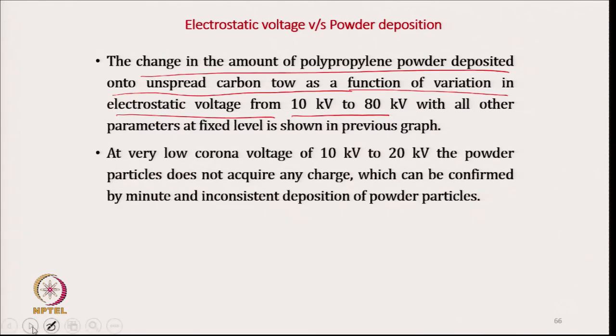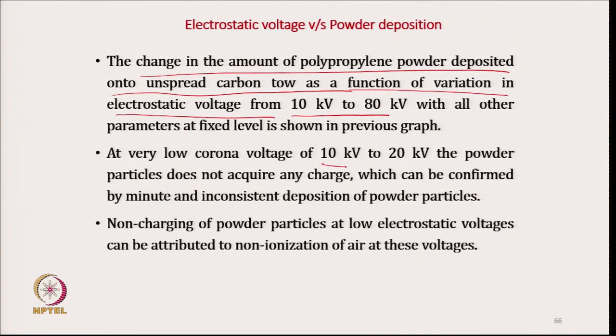At very low corona voltage, from 10 to 20, the powder particle does not acquire any charge, so there is no deposition. Inconsistent deposition was there, as no charge was there. Non-charging of powder particles at low electrostatic voltage can be attributed to non-ionization of air at this voltage. That is why up to 20 there was no such deposition.